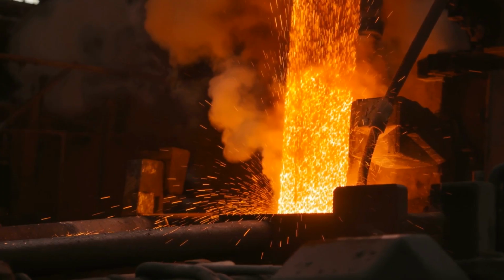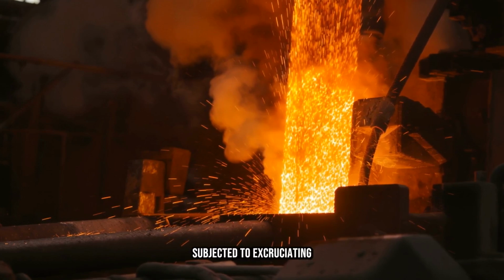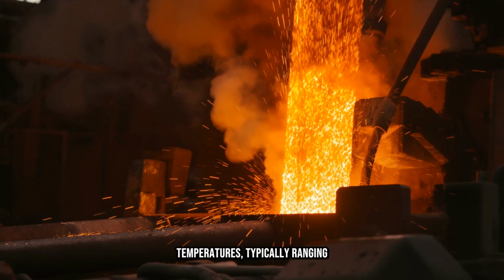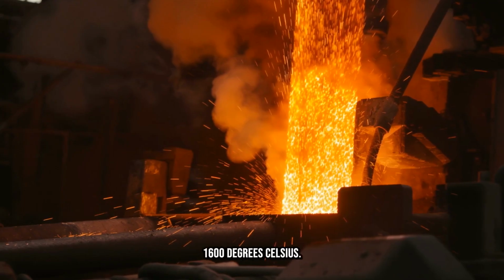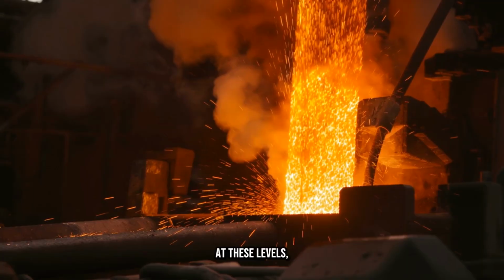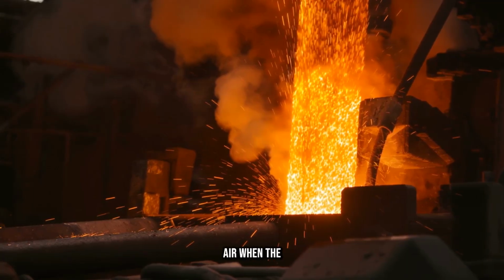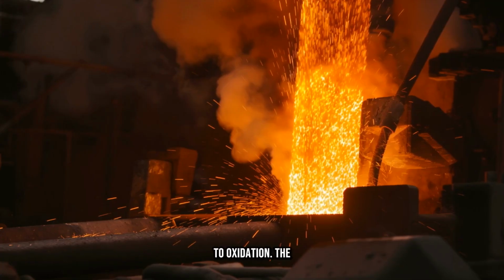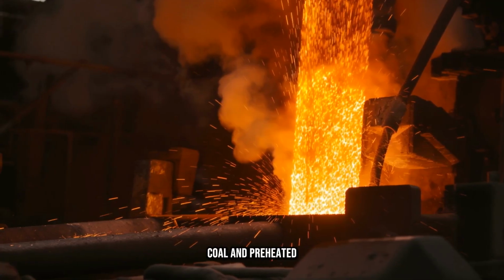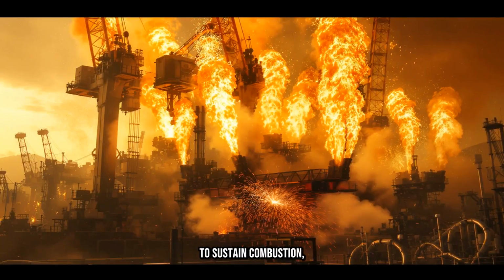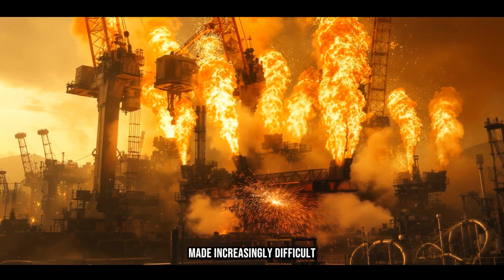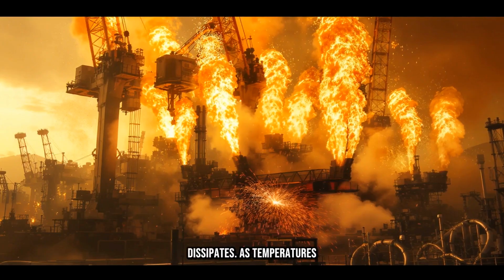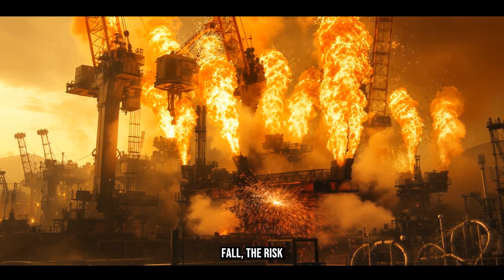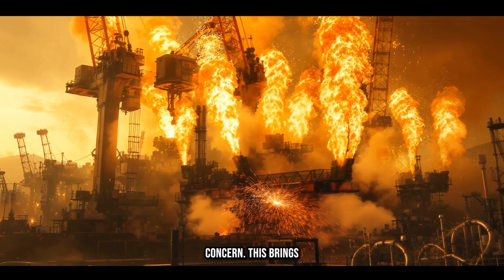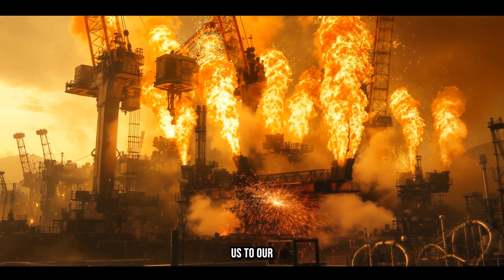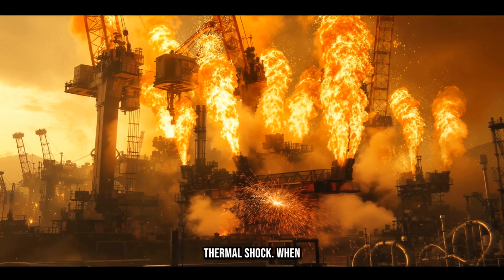The heart of the furnace, the hearth, is subjected to excruciating temperatures, typically ranging between 1500 and 1600 degrees Celsius. At these levels, any exposure to air when the furnace is turned off would lead to oxidation. The coal and preheated air would also need perfect conditions to sustain combustion, made increasingly difficult once the heat dissipates. As temperatures fall, the risk of thermal shock becomes the prime concern. This brings us to our first critical point: thermal shock.